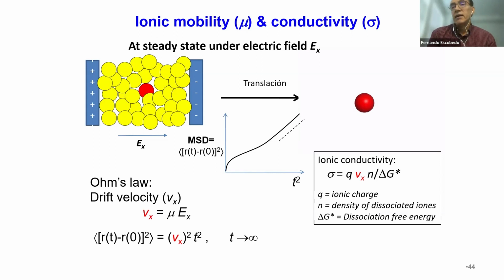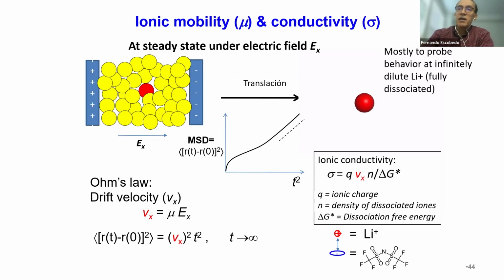And the formula for the conductivity is as follows. So it basically says that it's proportional to the ionic charge, of course, is proportional to this drift velocity, and is proportional to n, which is basically the number of these dissociated ions you will have in the system. But it's inversely proportional to delta G star, which is this dissociation free energy barrier. It's basically the same delta G star that I talked to you about before for the other system of photoresists by using this PMF calculation. So clearly you need to have all these elements, and of course they will be applied to the dissociation of lithium with the TFSI. And this kind of calculation can be used in many situations, but mostly we use it to probe the behavior at infinite dilution of the lithium. So assuming that it's in a fully dissociated state.